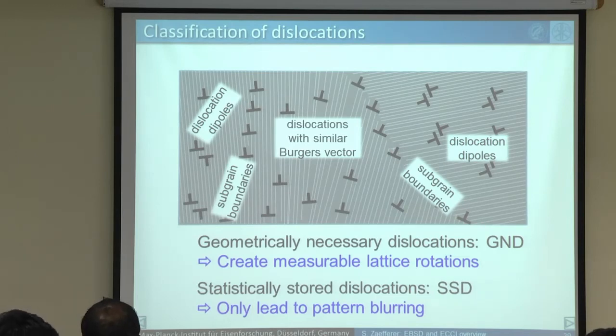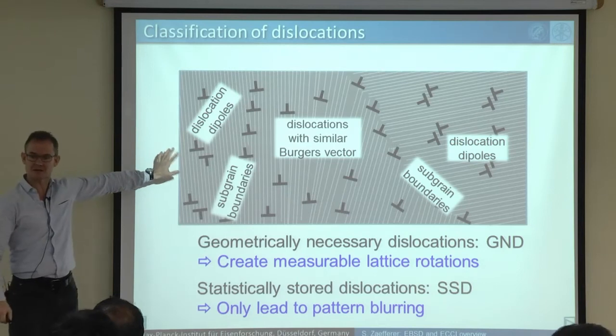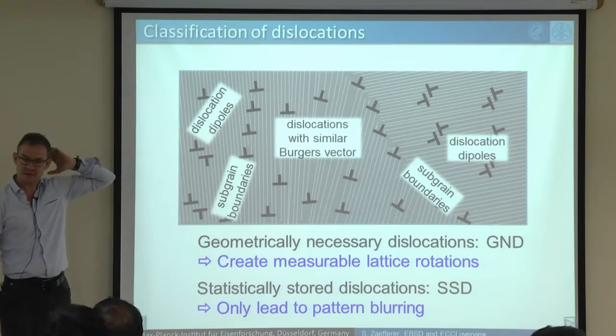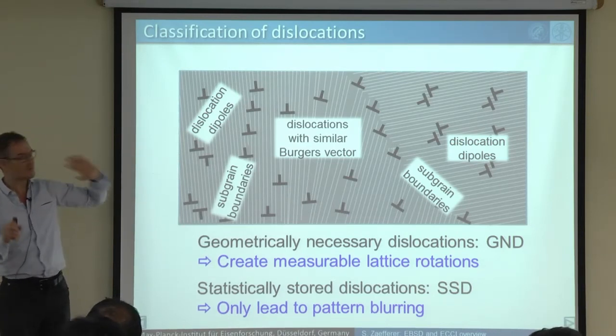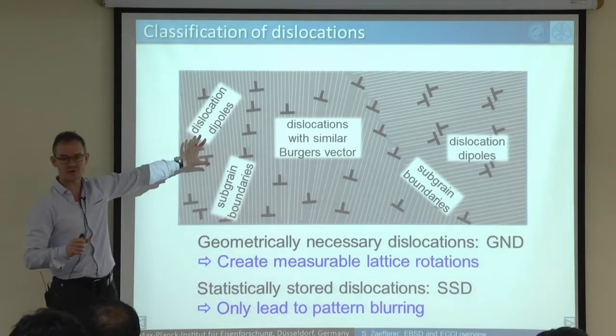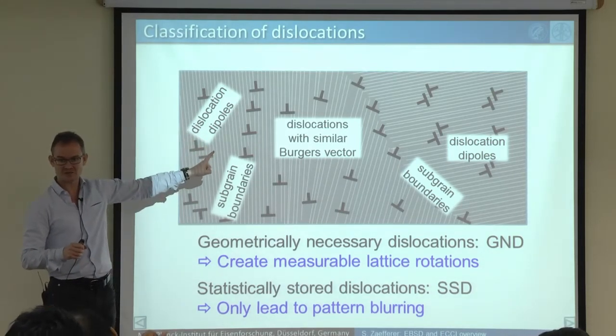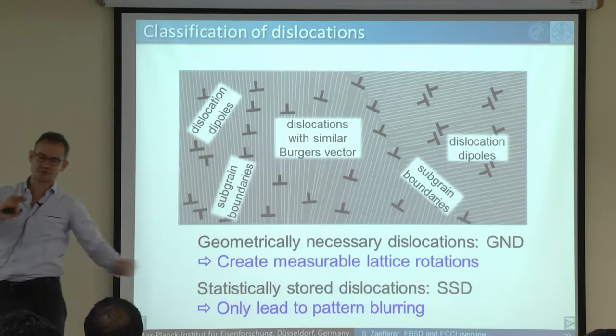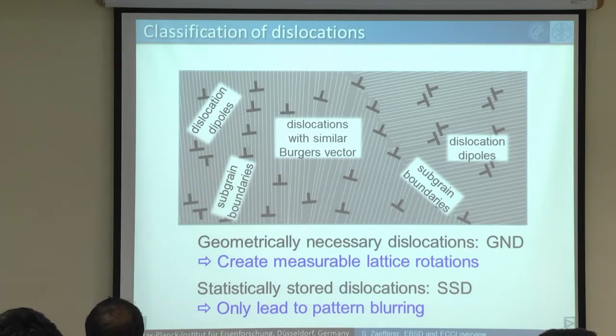Now we are using, actually I should tell you something disappointing. Many people think, if I measure with EBSD, I measure the GNDs, then I get an idea how much is the total dislocation density. And this is actually not true, because all these dipoles are usually much more numerous than the others. Usually we find that we have about 10 times more dislocations than we have GNDs. So this is very often a typical finding.